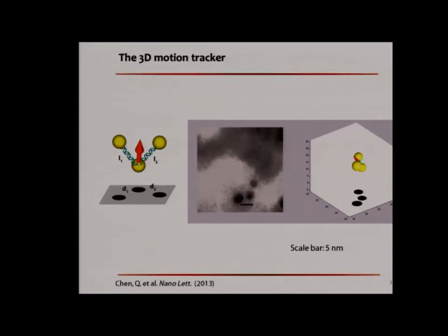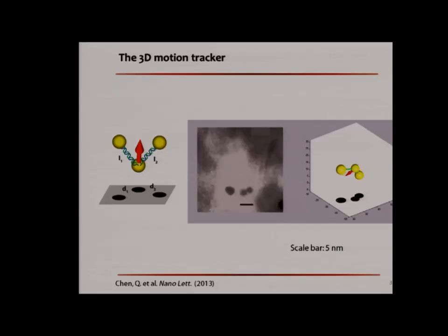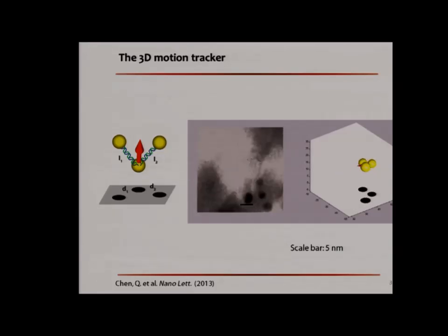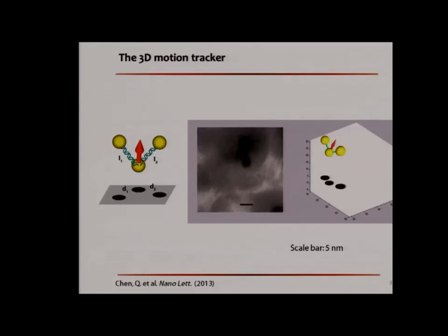A side note here is such 3D analysis was not possible before using conventional TEM, because in a conventional TEM, even if you start from a 3D structure, the structure can get flattened and collapsed during the sample preparation, leaving you no 3D information at all.